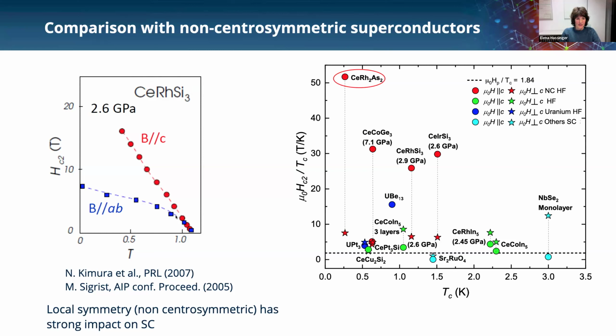And there you have a similar behavior where critical fields along the C-axis seem to be only orbitally limited and very large. And for fields in the plane, we have this strongly Pauli limited feature, but the Pauli limit is enhanced compared to the BCS Pauli limit.